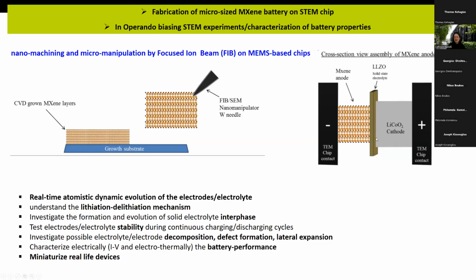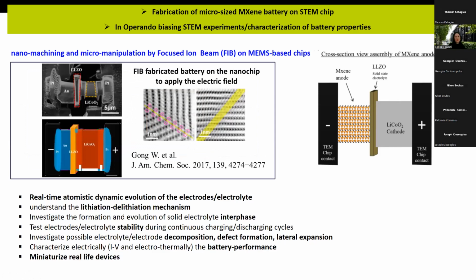What happens with the interfaces, because the interfaces are a big problem for all solid-state batteries, if we have formation of defects, if they trap lithium, and so on. This is, again, a very challenging and quite novel step, because so far there is only one group that managed and published doing such a process. You can see here the group of Gong et al. They managed to build a nano-sized battery on a chip with a gold anode, and after the in-operando experiment, they studied on the nanoscale the formation of different defects and if they trap lithium.